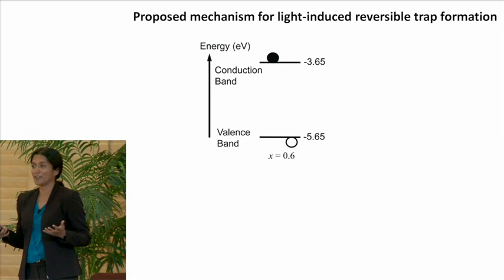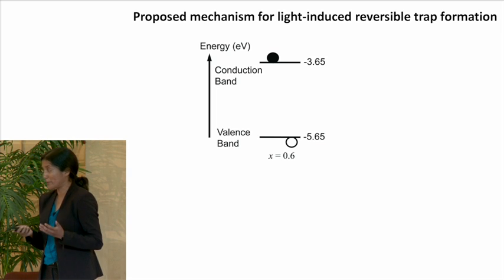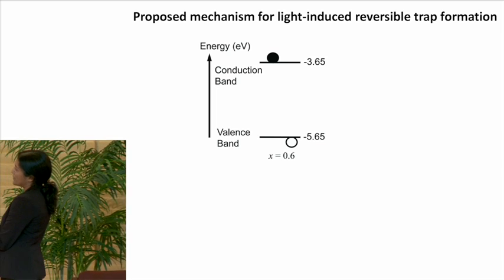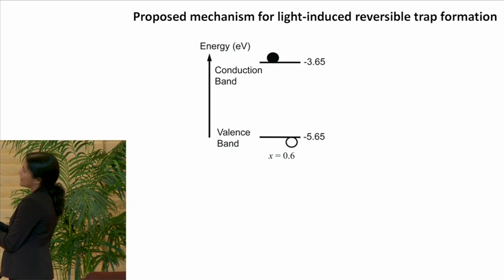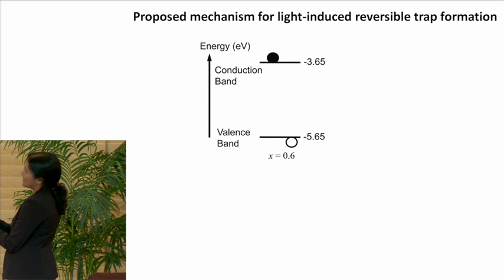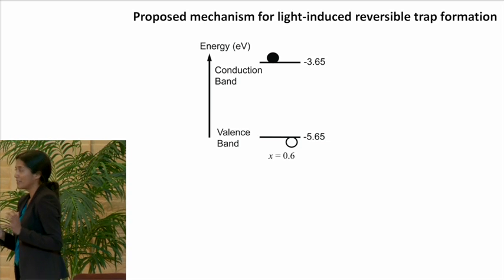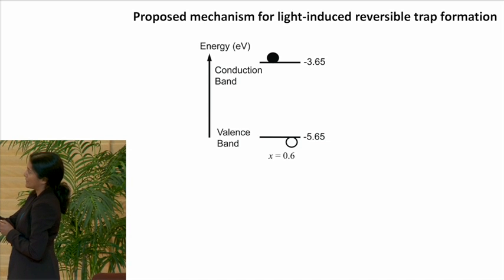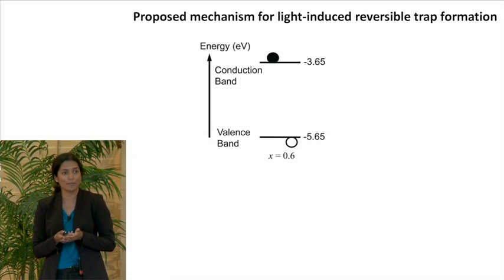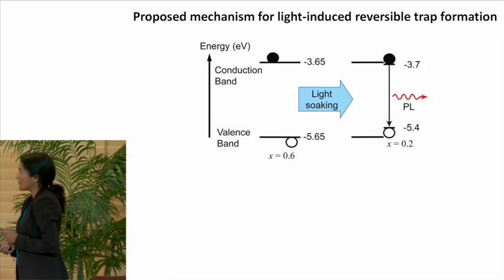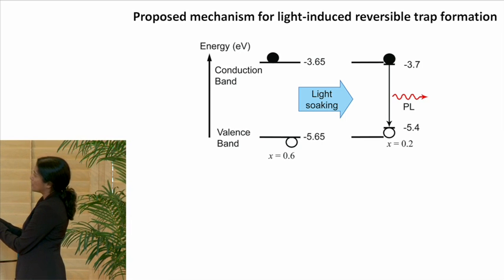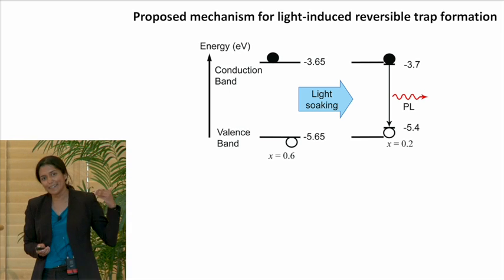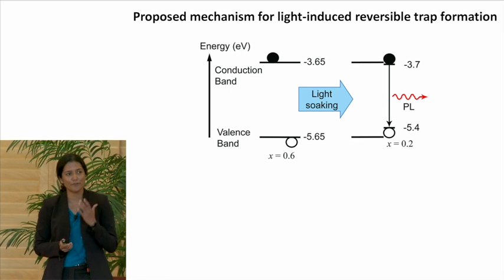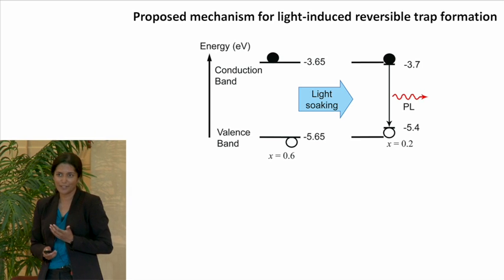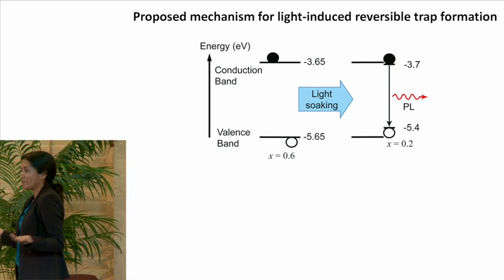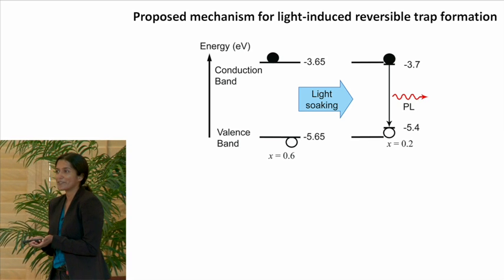So we went to the electronic structure of this material to try and understand what might be going on here. And here I show you for the x equals 0.6 material, the valence band as well as the conduction band. When we hit this with light, there are holes in the valence band and electrons in your conduction band. We know that initially, the photoluminescence comes from these electrons falling from here to here, but in time, we get this low energy photoluminescence band, which means we're forming a trap. So here's my trap. We have some state where the holes fall into a state with lower energy. We know that the energy of this photoluminescence corresponds to the same energy as the photoluminescence from an x equals 0.2 material. So we asked the question, maybe why not form the x equals 0.2 material, but only under illumination?